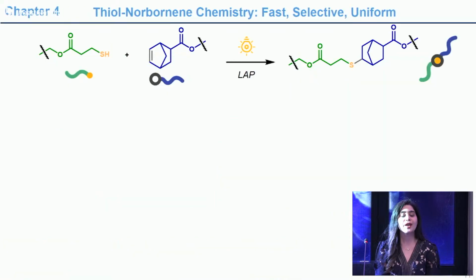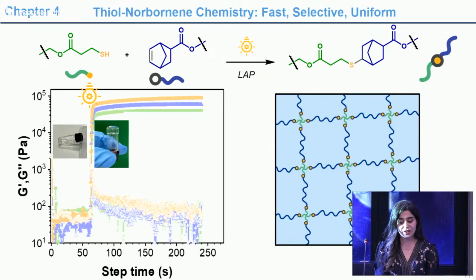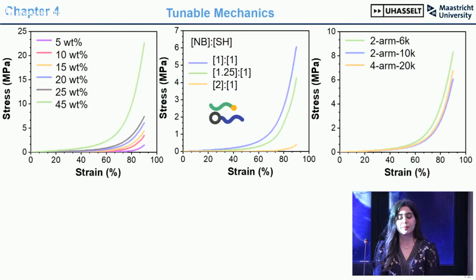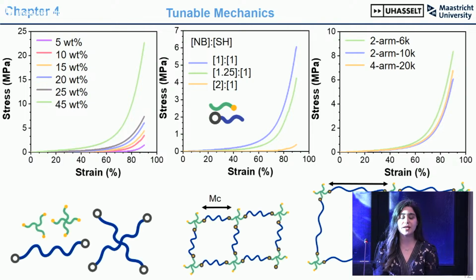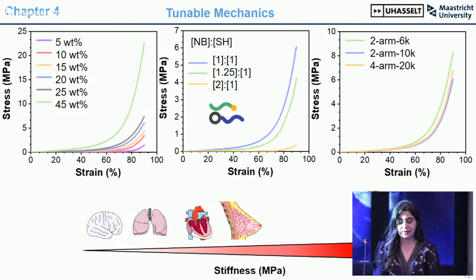collapse. To push this concept of network uniformity further, in Chapter 4, I developed robust hydrogels, but this time using thiol-norbornene chemistry, where gelation happens in seconds under visible light exposure to give us these uniform structures. But besides the fast gelation kinetics and uniform structure, this system also offers tunable mechanics, meaning that with minimal modification to the system, such as adjusting polymer contents, molar ratio of reactive end groups, and also architecture and molecular weight of the building blocks, I can precisely tailor the mechanics. This allows me to not only target load-bearing tissues, but also a variety of other tissues.